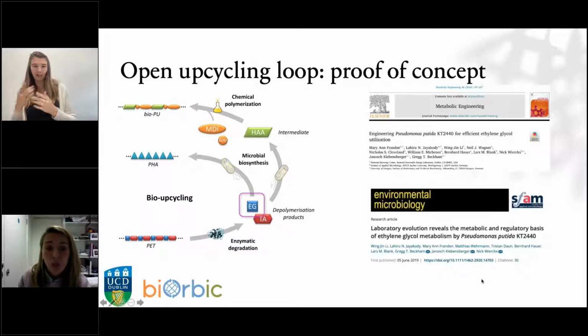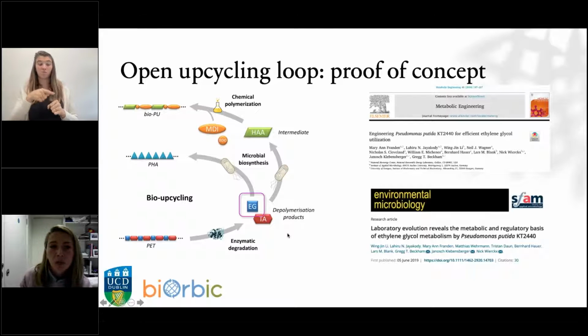Now, what else do we need to do to improve the process? Well, again, look at the metabolism of bacteria and how quickly and efficiently they utilize ethylene glycol and terephthalic acid. Ethylene glycol is an alcohol, it's a diol, it's a short molecule. Most bacteria, if they have a pathway to metabolize ethylene glycol, use it just as energy. But what we need is that ethylene glycol becomes an efficient substrate. And again, you have two seminal papers that came out of Greg Beckham's lab and Nick Wierckx's lab, and they have engineered bacteria for very efficient utilization of ethylene glycol. And now it's a different Pseudomonas, again very powerful, Pseudomonas putida KT2440, that can now grow with half a molar and 1 molar ethylene glycol.